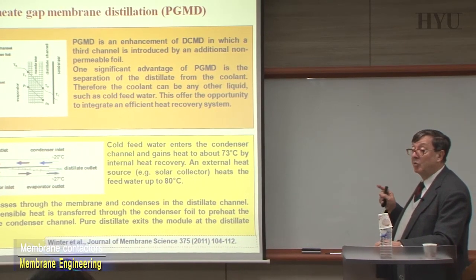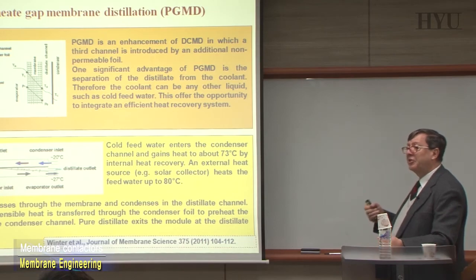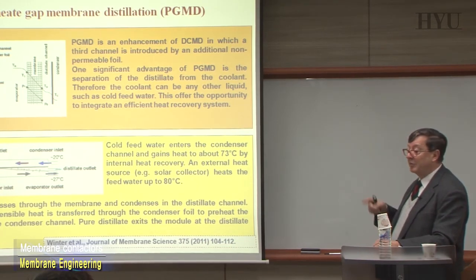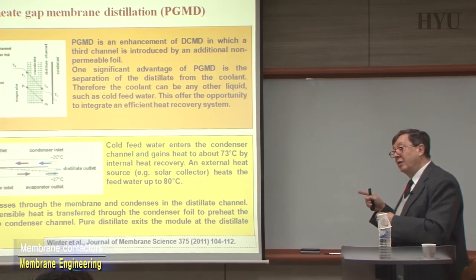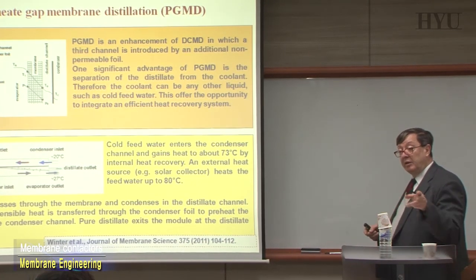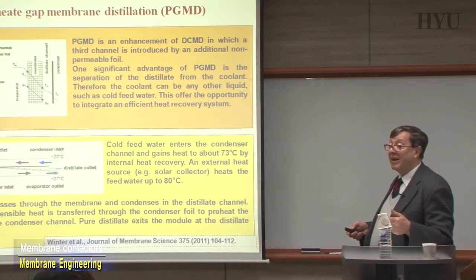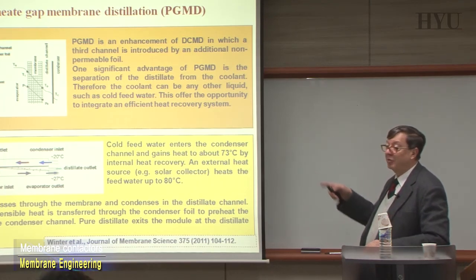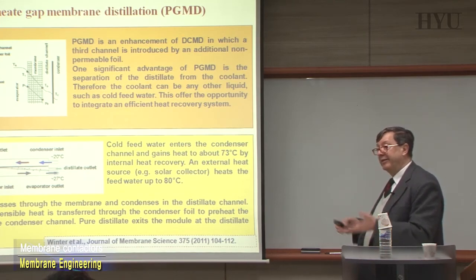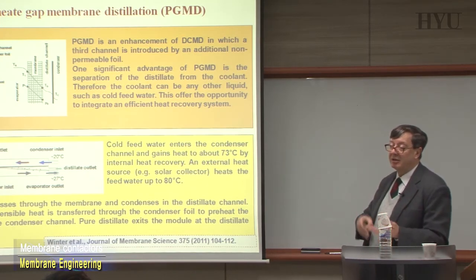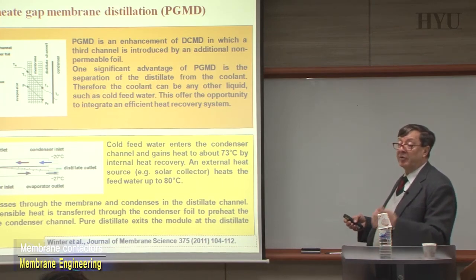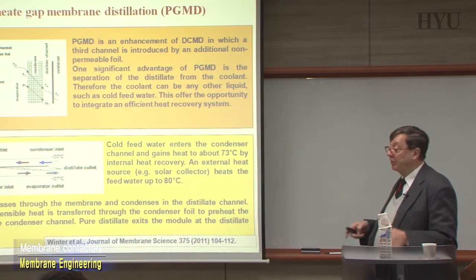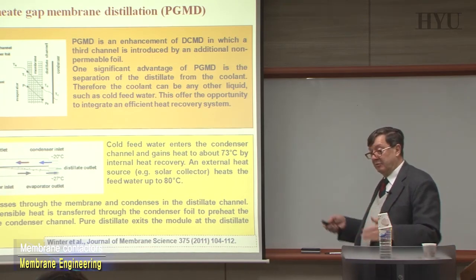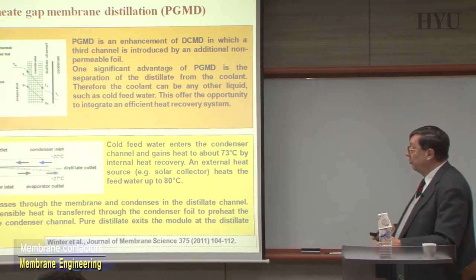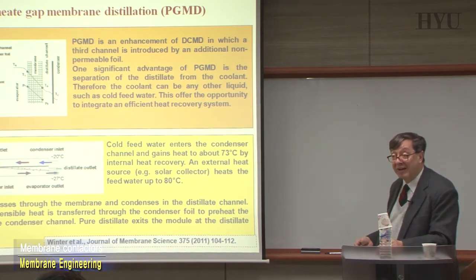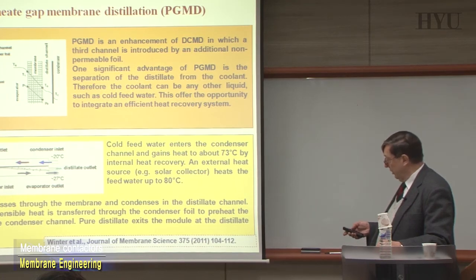This system really is working nicely in terms of heat recovery, but if you look at real life, you will realize that at the moment what you gain from the heat recovery system, you lose in the transmembrane flux. The overall transmembrane flux goes down when you have this kind of configuration with this third plate, and the recovery of the heat is not completely positive if you consider that you are losing transmembrane flux, to the point that these big modules are still under study. A lot of people are looking at them, but if you want to find a real plant, you don't find them because some work still has to be done.